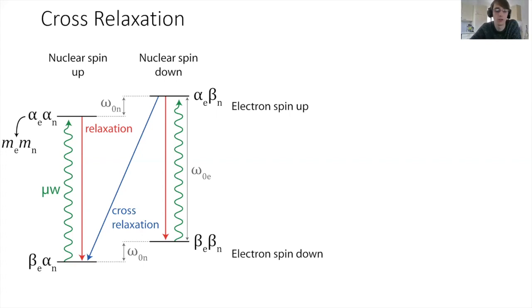So assuming the zero quantum relaxation will dominate, I don't want to tie myself down. Maybe if you have transition metals, I'm not sure necessarily whether Fermi contact will dominate. I still think it will, but I'm less sure. But assuming that zero quantum cross-relaxation dominates, then it's solely dependent on the sign of the gyromagnetic ratio of the nucleus. And so for lithium, that's positive, and we get positive enhancement. If you had a negative gyromagnetic ratio, you'd have a negative enhancement.